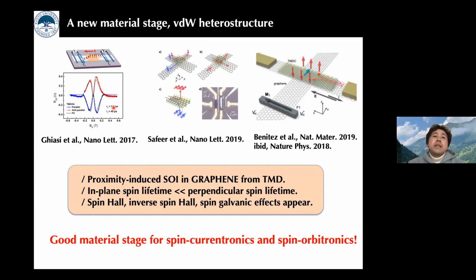But I should emphasize the other type of new material platform, namely the van der Waals heterostructure. So here I show some important works, and as you see, here they use the heterostructure between single-layer graphene and TMDs. And because the proximity spin-orbit interaction is created in graphene from TMD, the spin lifetime perpendicular to the graphene plane is much longer than that along the in-plane direction. And also the proximity SOI allows the observation of the spin Hall effect, inverse spin Hall effect, and spin galvanic effects, and now this van der Waals heterostructure is a good material stage for spin currentronics and spin orbitronics.